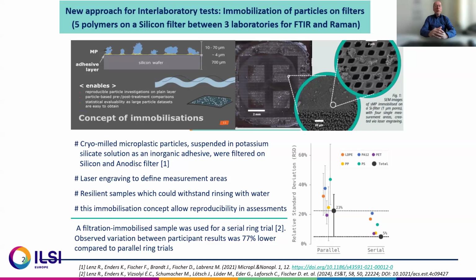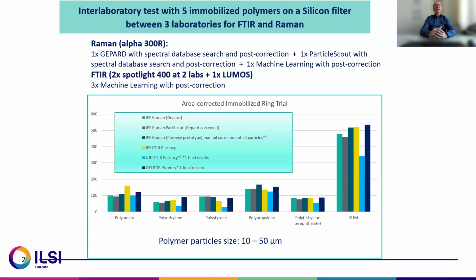We did a first ring trial for that, and we could lower the observed variations between the participants' results by 77% compared to a parallel ring trial where everybody gets a sample and analyzes the sample by themselves. So that is a very good idea for particle-based laboratory tests. Here are first results between 3 laboratories with FTIR, with Raman, with spectral database search, with machine learning. And you can see that the results are comparable.